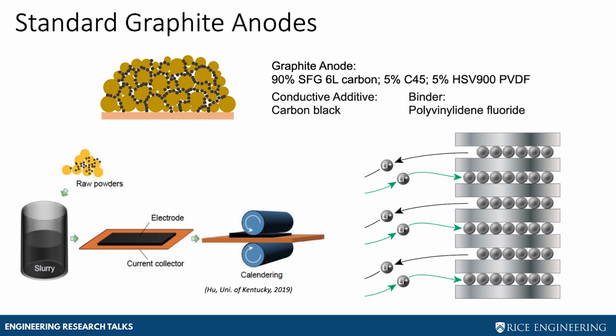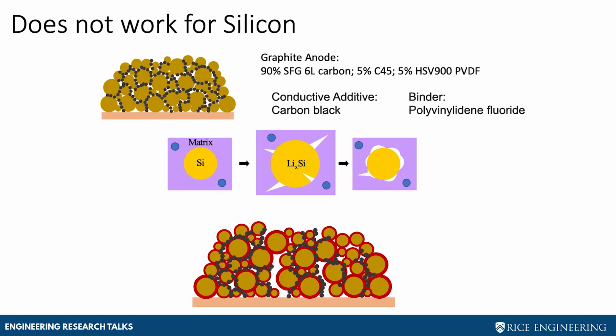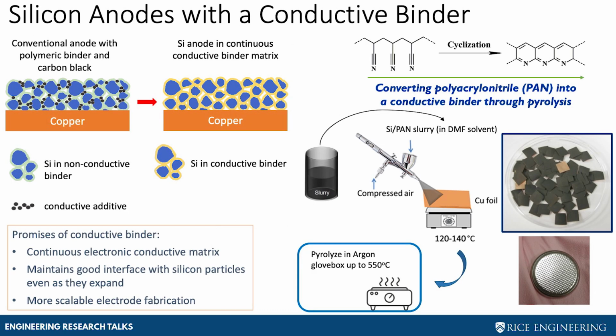When we did this with our silicon instead of graphite, it just didn't work. Silicon with that large volume expansion led to lots of fracturing and stresses in the material that was not able to support the cycling. So instead, I had a very talented postdoc who, looking in the literature on conductive polymers, was able to find this particular polymer, polyacrylonitrile. I'm going to call it PAN.